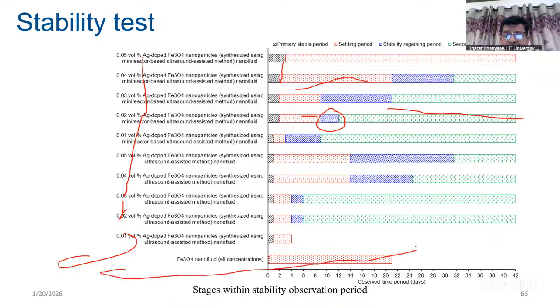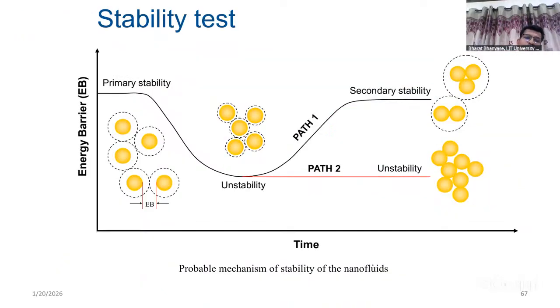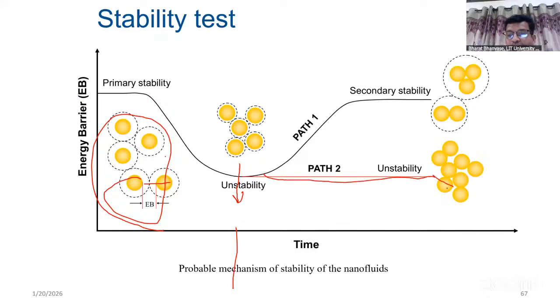But Fe3O4 alone is unstable, so there is no doubt a settling period is present. With the addition of Ag-doped material, the settling behavior gets improved. From this we have predicted a mechanism: initially there is stability, where an energy barrier is calculated between the two particles. Once that energy barrier is disturbed, an unstable period occurs, which continues in the case of Fe3O4. But in another case, secondary redispersion of these clusters was observed, which is nothing but the secondary stability period.